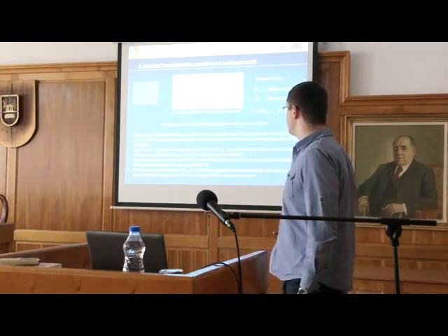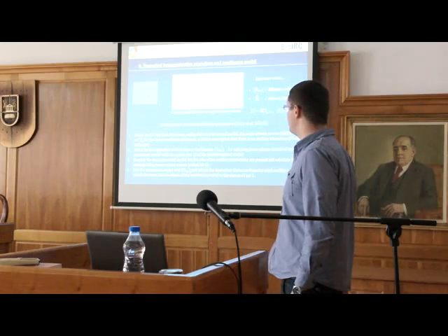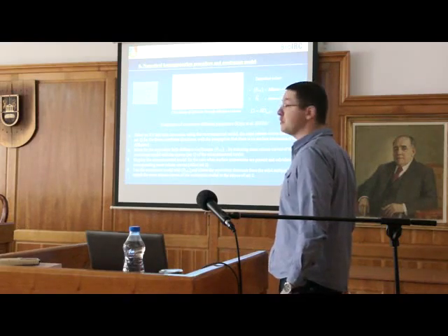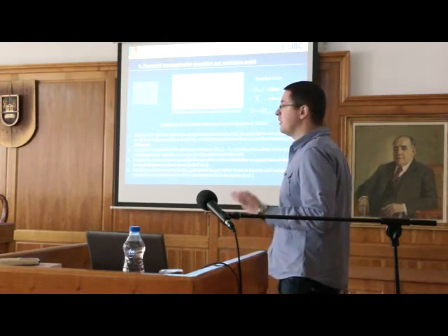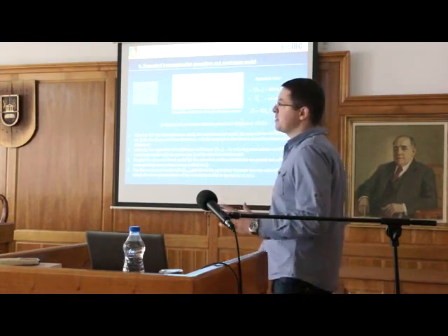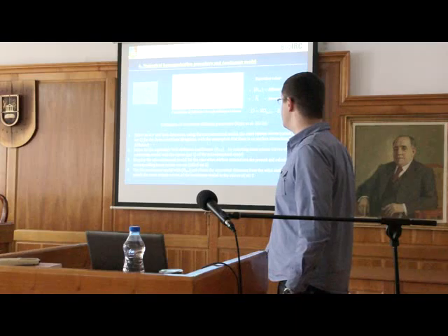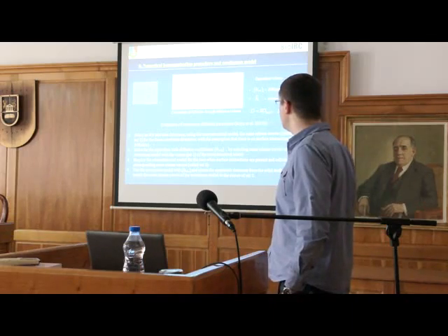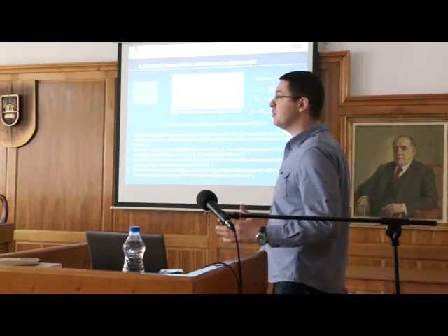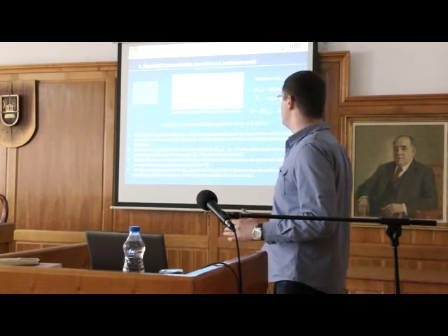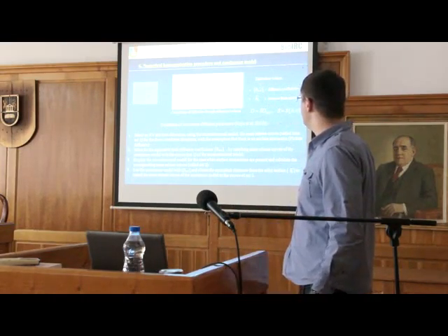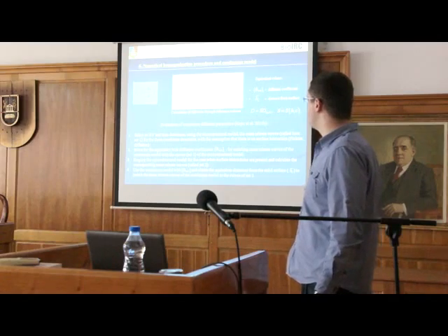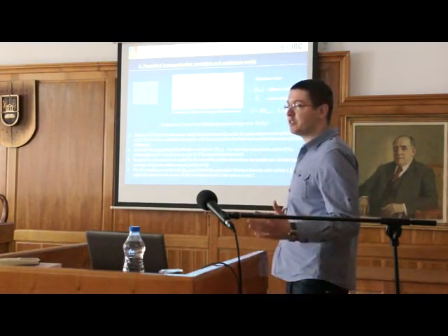For example, the first step is that for this selected reference volume, we assume that there is no surface effect, so there are just fibers in the system. We just have porosity. So for the system without surface effects, we first calculate the release curve, and then for the same continuum model without fibers, we fit the diffusion coefficient in order to have a comparison between curves of the microstructural and continuum model.